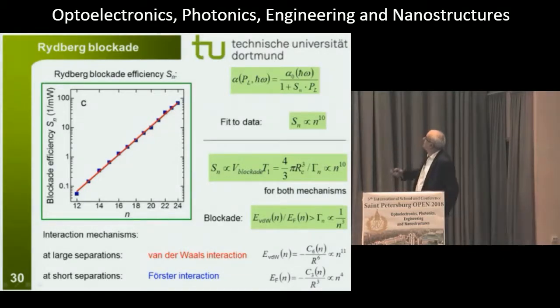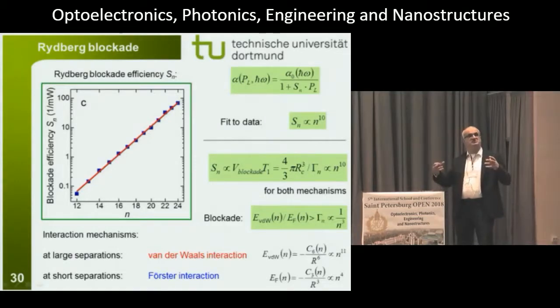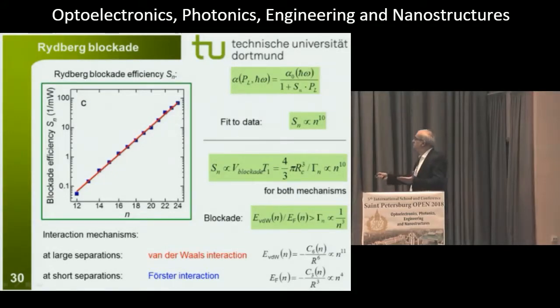We also developed some theoretical model for this, which basically tells you that this blockade efficiency is proportional to the lifetime of an exciton times the size that this exciton has. How big is it? And from this you find indeed a good agreement with the experimental result. But at that point, we were sort of surprised that it doesn't matter what interaction you assume between the excitons. So we use, for example, a van der Waals interaction. It gives you this n to the power of 10 dependence, but you can similarly use a Förster type of interaction, which has a totally different scaling dependence with the separation between the excitons. It also gives you an n to the power of 10 law. So this n to the power of 10 is an extremely stable quantity.